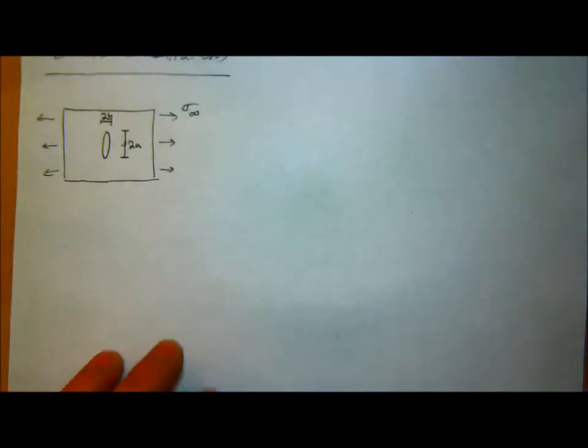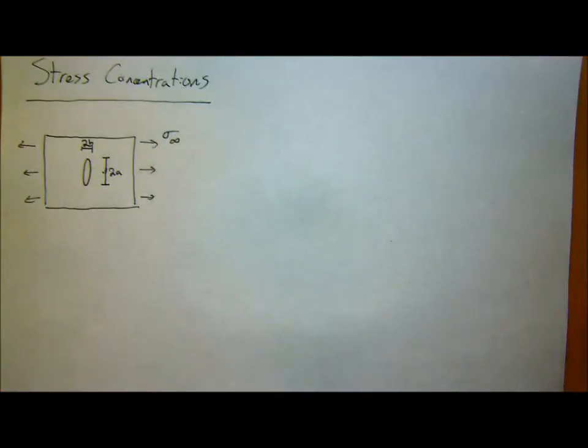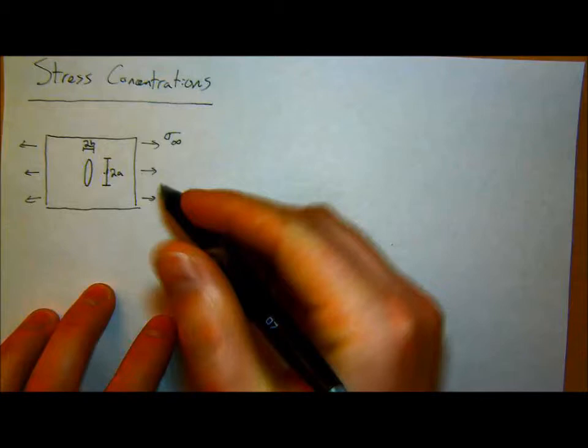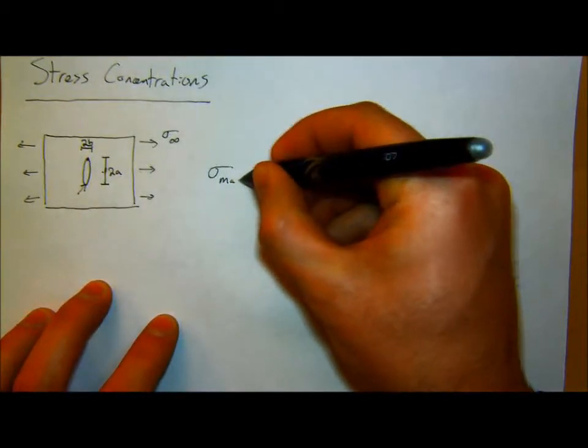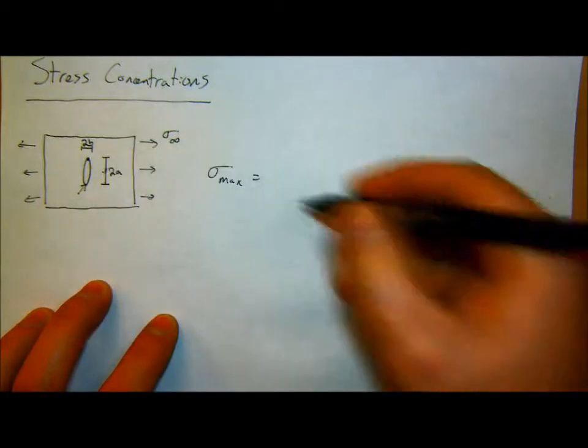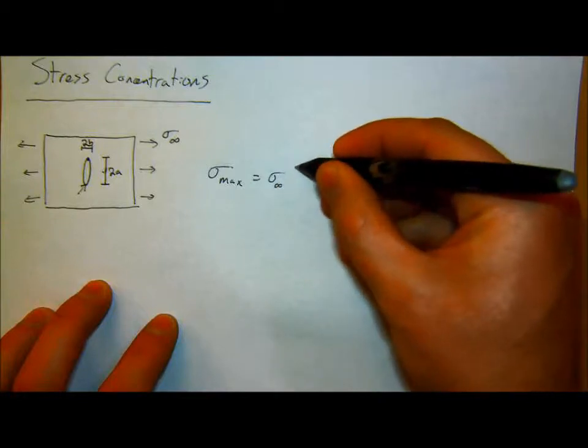Okay. So, stress concentrations. Cool. I think this notation is actually flipped from how I had marked it on Monday, but just roll with it. It's more for the sake of how we define fracture. So now I'm going to define, here at the root, you remember our maximum stress concentration, sigma max, is now here at the top and bottom edges of that elliptical hole, and this is equal to sigma infinity times 1 plus 2 times A over B. Again, this is flipped from what I had on Monday, just for the sake of fracture.